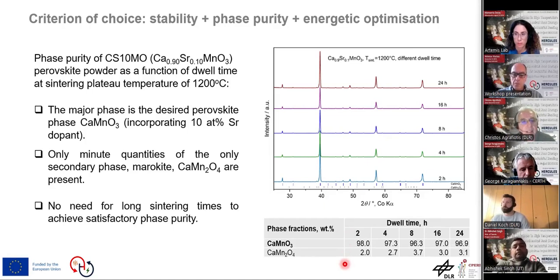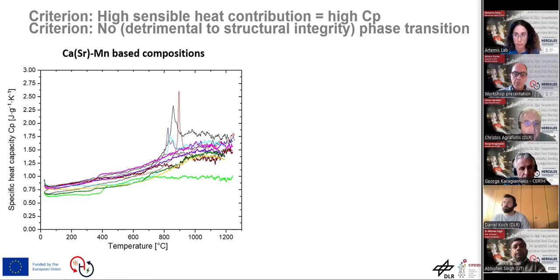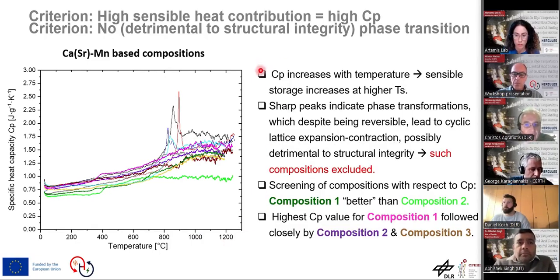Another criterion that we see in the next slide is the sensible heat contribution. As we said before, here we measure the CP of various compositions as a function of temperature, the temperature that we are interested in, from ambient to 1200. And we see that the CP increases with temperature, okay? Which is good because the sensible storage increases the higher the temperature that we want.